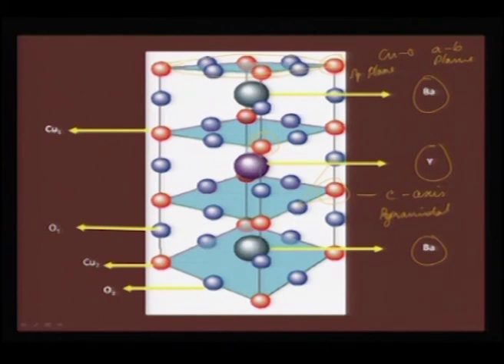Apart from that, we would also try to take a close look at the oxygen occupancy. You would see here, this is mainly based on the copper oxygen sheets that are prevailing in the AB plane, and there are also oxygens along the C axis, and the number of oxygens that were getting desorbed, as we saw in the earlier slide, denotes oxygen can actually be lost here, oxygen can be lost between these 2 sites, oxygen can be lost here also. So, there are different places oxygens can be labile, but as you saw, with each temperature region one particular type of oxygen is actually going.